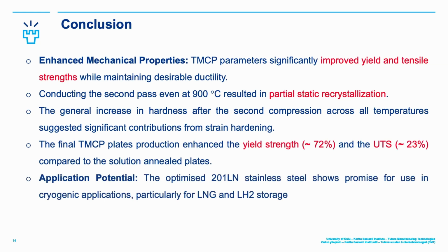So for conclusions, we were able to achieve enhanced mechanical properties for this 201LN stainless steel. The second pass of 900 results in partial recrystallization, despite this temperature being below the TNR, and a general increase in hardness for the second compression. The final TMCP production enhanced yield strength by 72% and the ultimate by almost 23%. And we are expecting that this could be a potential enhancement for cryogenic applications.